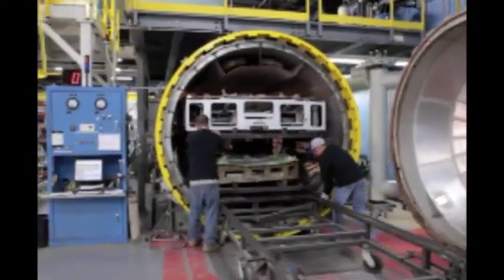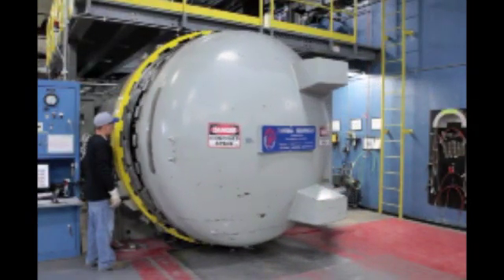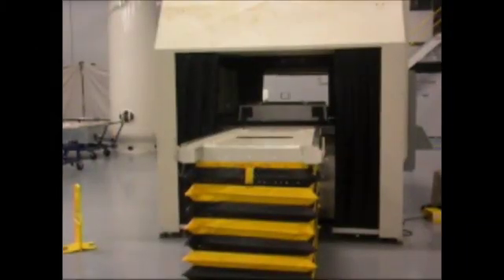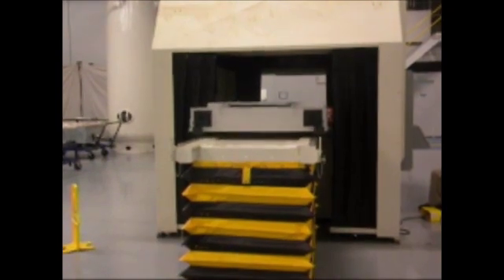If you think about carbon fiber, an autoclave is a giant oven. What I like to try and describe to people is, if you have a nice thick fillet, which is what carbon fiber really is, do you want to cook it in an oven, or do you want to cook it on an infrared grill? How are you going to get the heat transferred to the resin to allow it to flow and then cure quickly? What we've done is basically backward engineered what happens in the autoclave in a very slow convection process and gone to an induction process that allows us to rapidly heat and rapidly cool the tooling in a very confined environment, much like any other press that you would see, and take that cycle time down from 90 to 17 minutes.